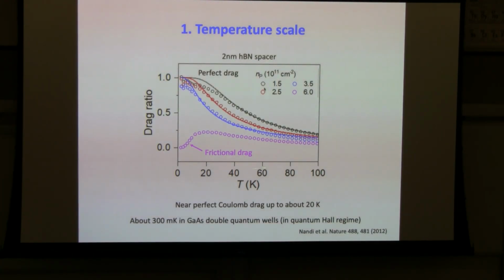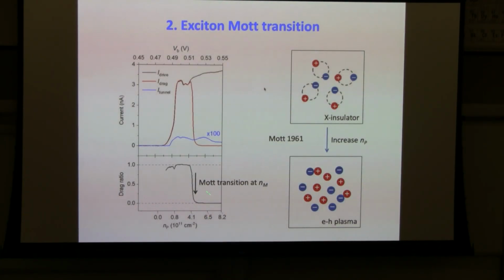Okay, and this frictional drag, I will come back to it immediately. Let me come back to this sharp transition from perfect drag to zero drag at this density. What's happening here is that with increasing exciton density, as proposed by Mott in 1961, there is an exciton Mott transition. At low exciton density, the electrons and holes are bound into excitons, but as you increase the pair density, at some critical density you go into an electron-hole plasma state. The electron-hole plasma state pretty much means the electrons and holes have zero binding energy, and as a result, you get zero drag in the low temperature limit.